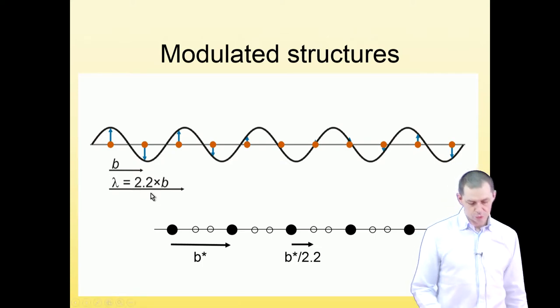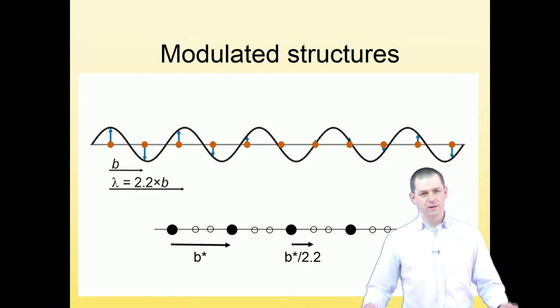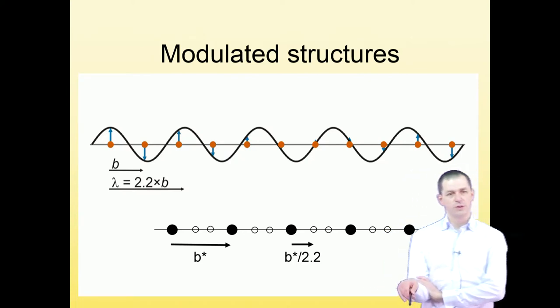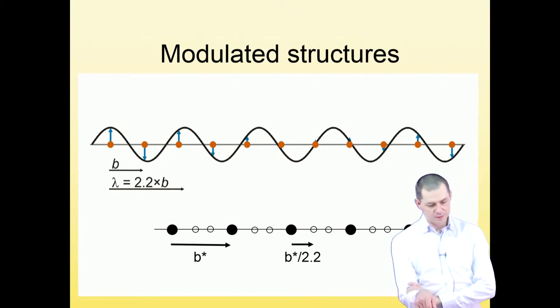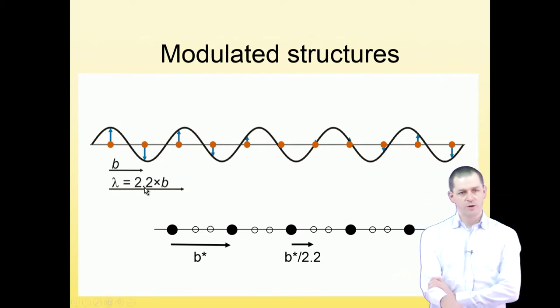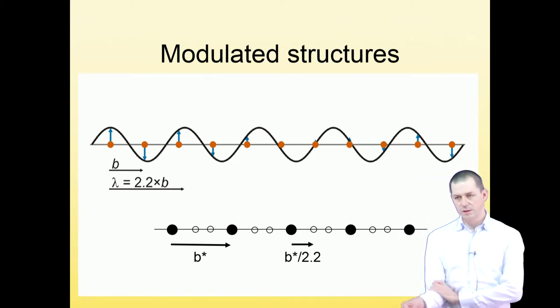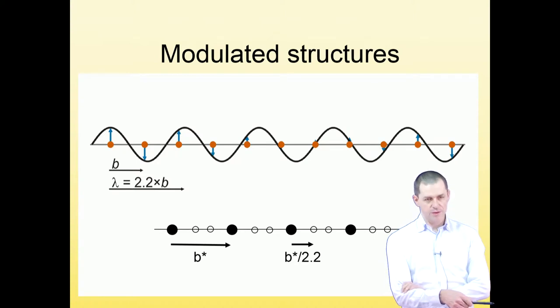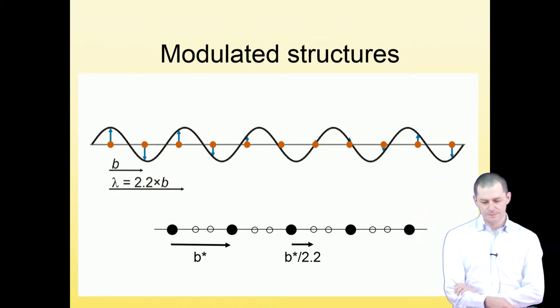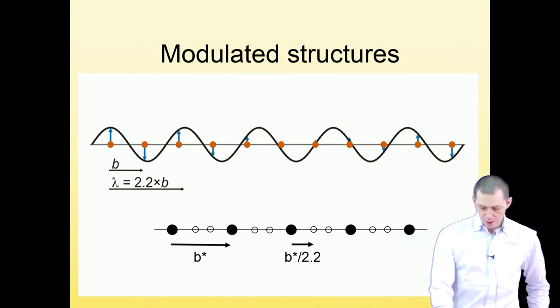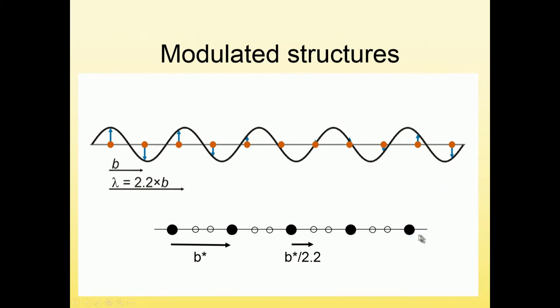Well, with the wavelength of 2.2b, we obtain a periodicity after 11 unit cells. But if this number here wasn't 2.2, but it was an irrational number, then we would obtain a purely incommensurate, never periodic structure. And the diffraction pattern looks like this. So again, we have the spots corresponding to the main periodicity. And in the middle, we get the satellite spots, which have the length that corresponds to the reciprocal of b divided by the wavelength of the modulating wave.